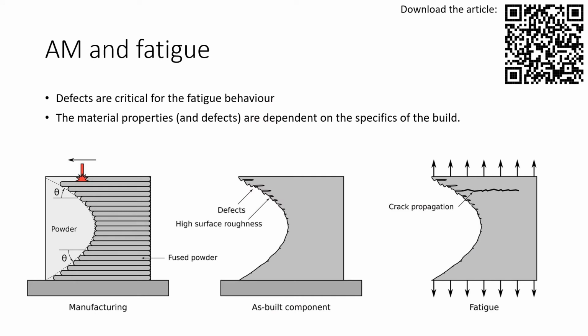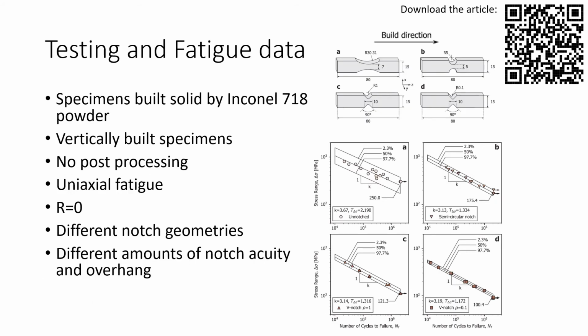Okay, so if we build a notch geometry by additive manufacturing, we're likely to have a higher amount of defects in the downskin regions than in the upskin regions. And if we subject the specimens to fatigue loading, as shown to the right, the defects are likely to be the fatigue initiation site. Okay, so these are some specimens, different specimens, and the fatigue results.